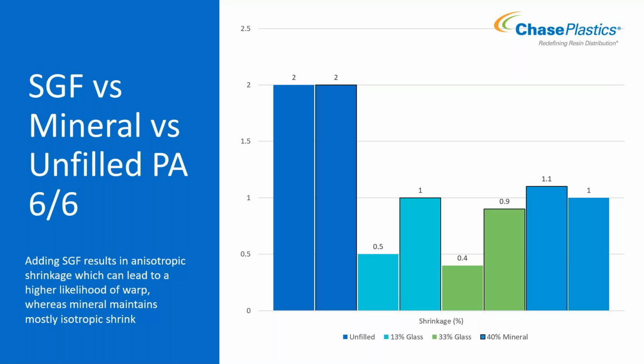So if you come into an issue where you're having way too much warpage and it's not working, maybe just the little boost that mineral gives you in stiffness and strength is enough, and you can maintain not having really bad warpage using a mineral. There's a few different ways to go about doing it - maybe add mineral in, or in a few slides when we talk about impact modifier, we can also help make sure the shrinkage is not as bad. So a few different ways to go about that, but mineral will not add anisotropic shrink to your performance.